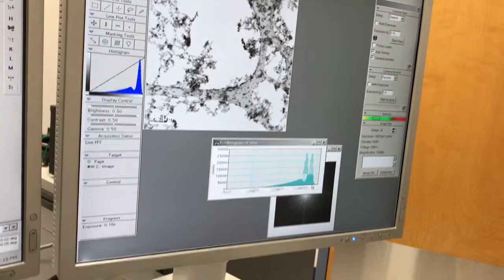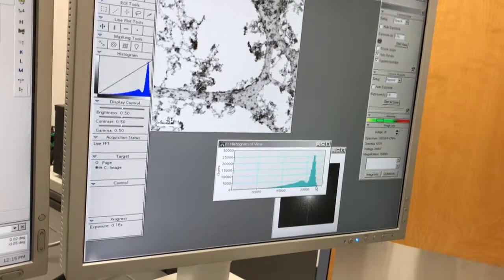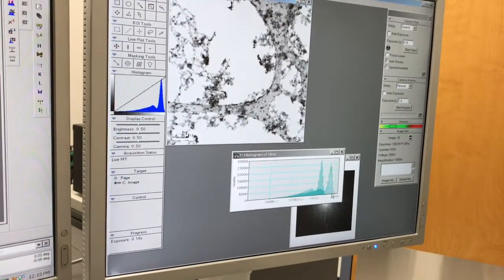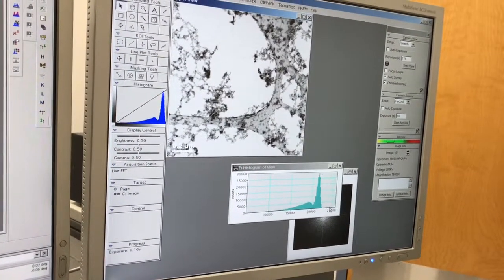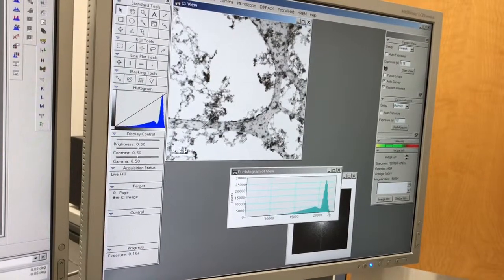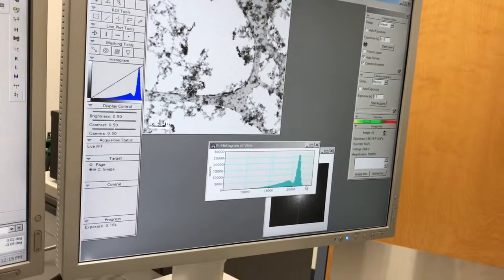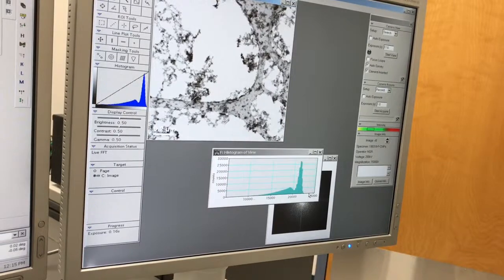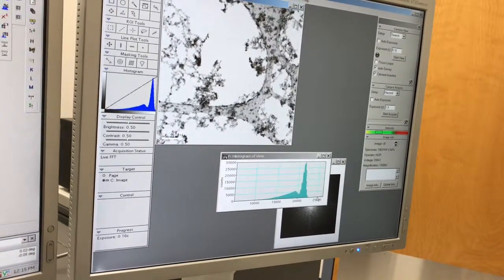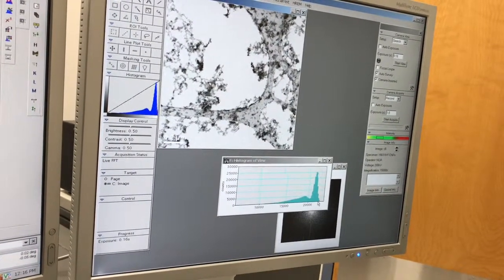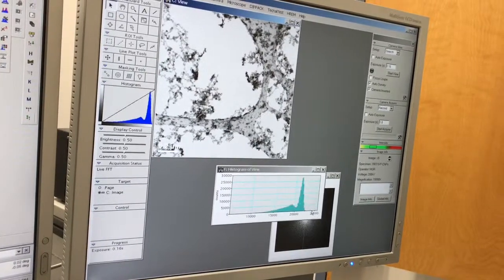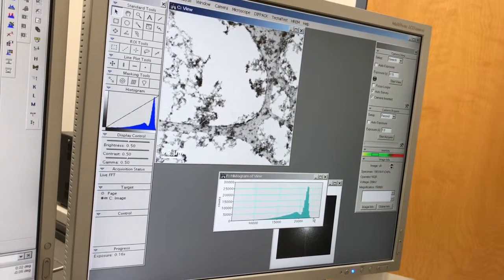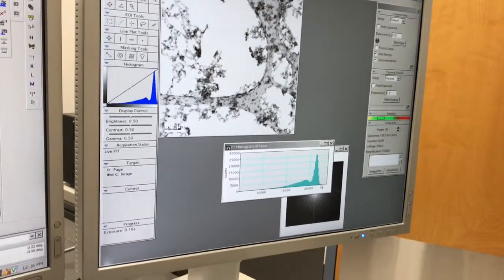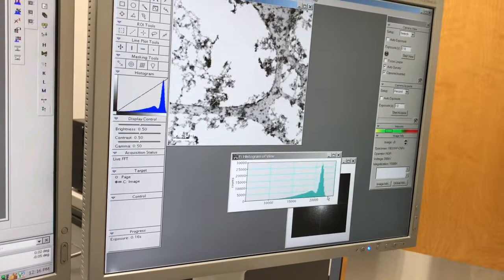25,000-ish. Generally speaking, with most digital cameras, the optimal grayscale value range is around the middle value of the dynamic range. So in other words, if 65,000 is the max, I'm shooting for something in the vicinity of 32,000. Now in practice, I usually don't have to go that high to get a decent image.